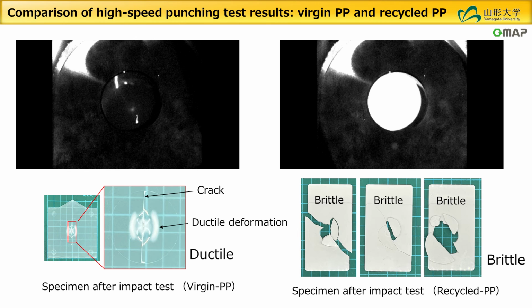But if you try to create holes in a test with virgin PP, holes are made, but the plastic itself doesn't break. The entire polymer retains its shape. But with the recycled PP, once a hole is made, it breaks apart. So it's very brittle. At the start, the strength levels are very different between the two. So in the case of recycled products, they can't be used like the virgin product.